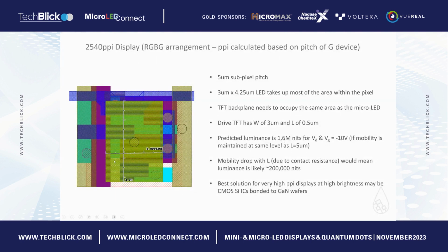Yeah, I think this one is a bit of a theoretical calculation, and it assumes that mobility doesn't go down with channel length, which it probably will to some extent. So hence I've said that more realistically, probably about 200,000 nits for this. But the challenge of making it this size is the photolithography. You need to pattern the conductors to around half a micron and then have an overlay accuracy of probably about 1/8 of a micron. So you need to use a stepper system for this. If you're going to go to the whole bother of using a wafer stepper to pattern all of this, you may as well make a silicon IC instead as the driver system. So I would not advocate for using this for making very high PPI.